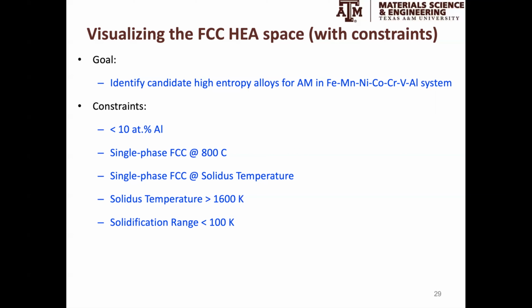From experience and from the literature, we know that alloys with less than 100 Kelvin of solidification range, or freezing range, can be printed.